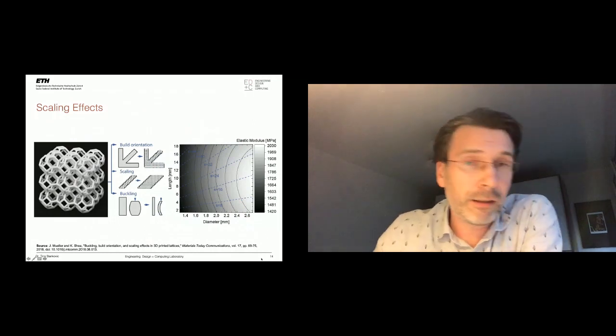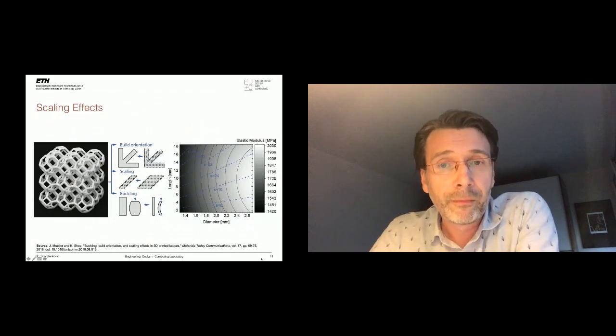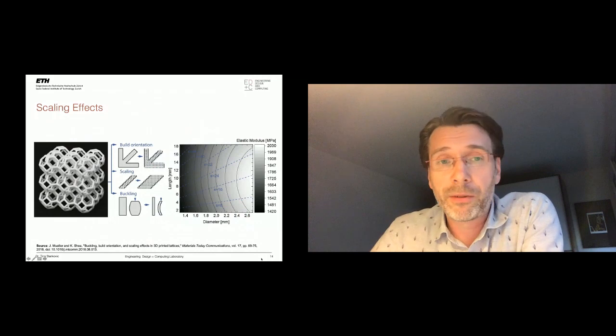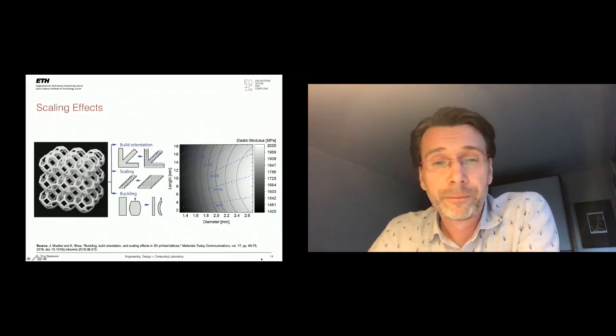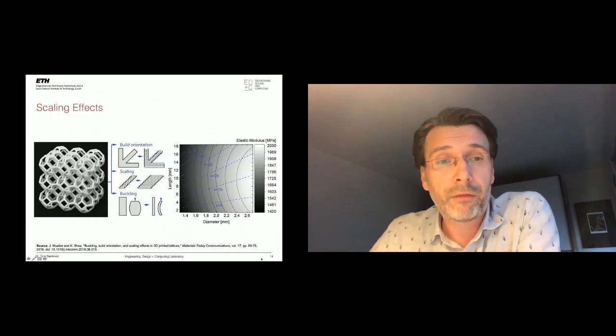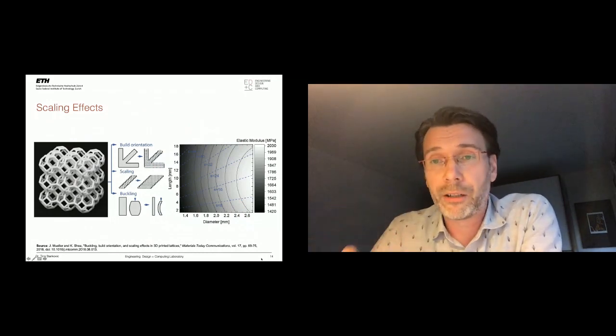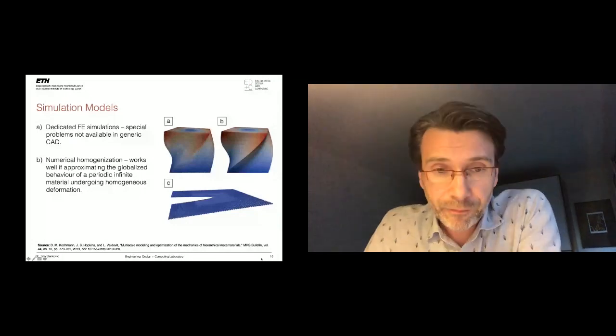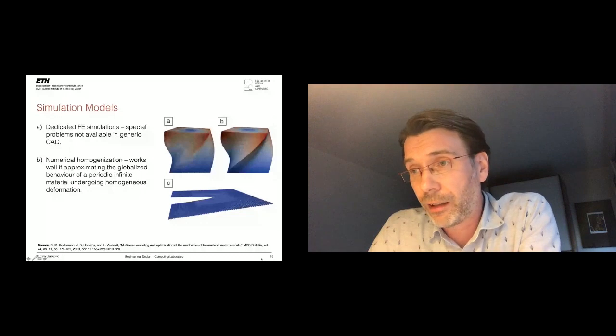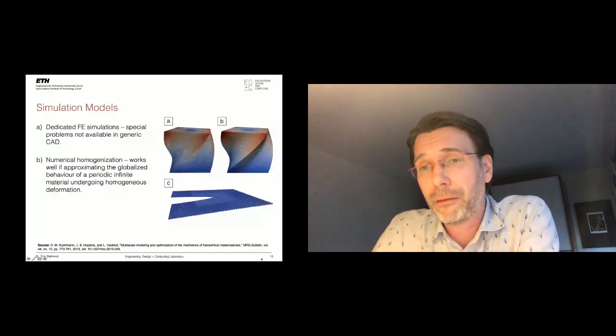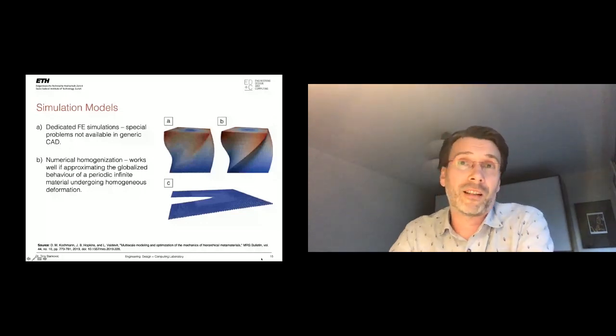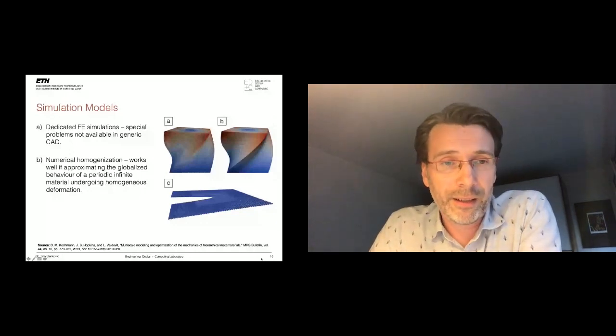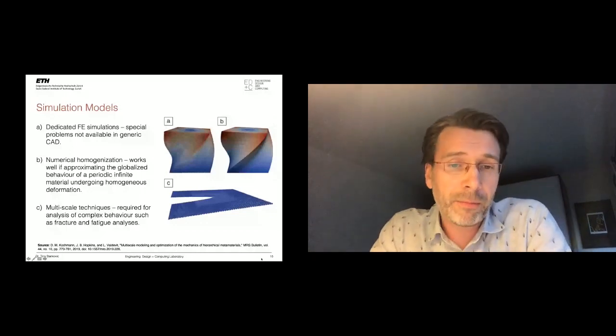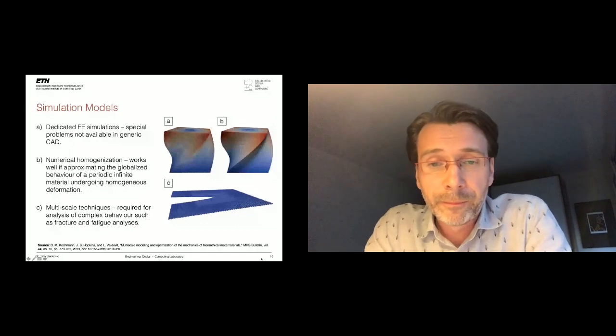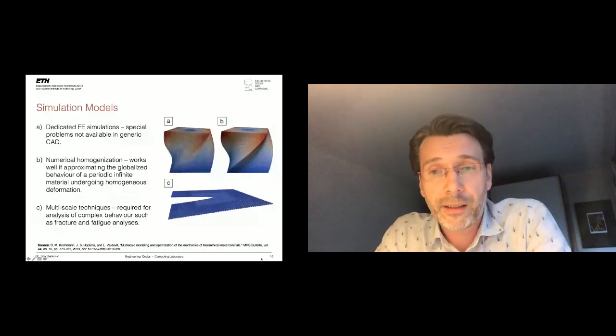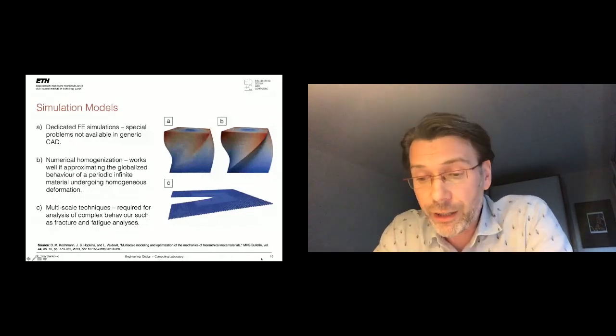This also relates to what we had before. There are different simulation models currently because the simulations are not accurate enough. So for instance, we need dedicated FE simulations. Special problems are not available in generic CAD, for instance, like modeling the behavior around the joints. Then we can use numerical homogenization, which works well if it approximates the global behavior with periodic boundary conditions. That does not happen if we have unit cells that are not of the same size, which normally happens in engineering problems, and we don't have enough of these unit cells. So actually the periodic boundary conditions are not periodic, and we can't apply these techniques. And third, we have multi-scale techniques that are required for analysis of complex behavior, such as fracture and fatigue analysis, which are not possible in the previous two. They apply different resolutions at different length scales and model the behavior of material using discrete bars.